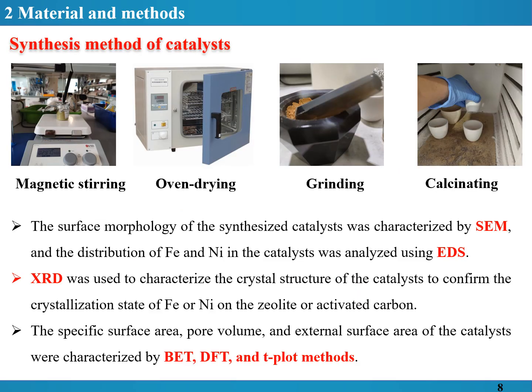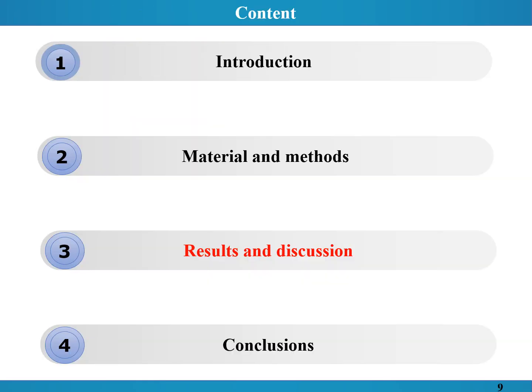Catalysts with different catalyst supports and metal loadings were prepared through the wet impregnation method. These catalysts were characterized in terms of their surface morphology, crystal structure, and specific surface area and pore volume by SEM images, XRD, and BET methods, respectively. And part 3 is the results and the discussion.